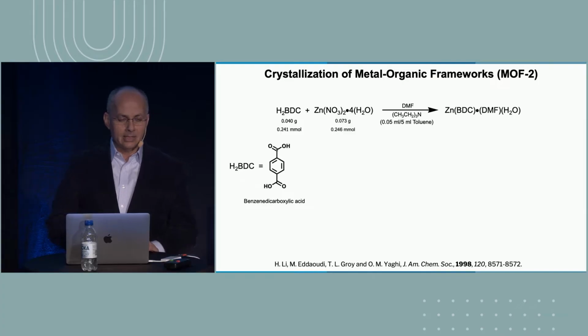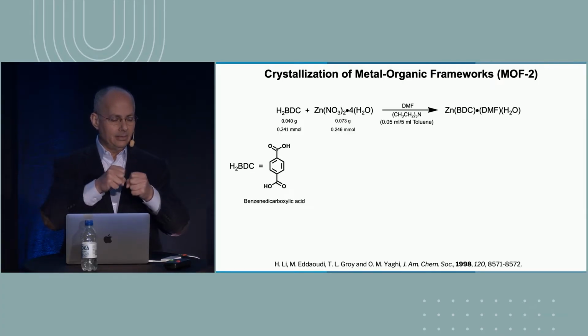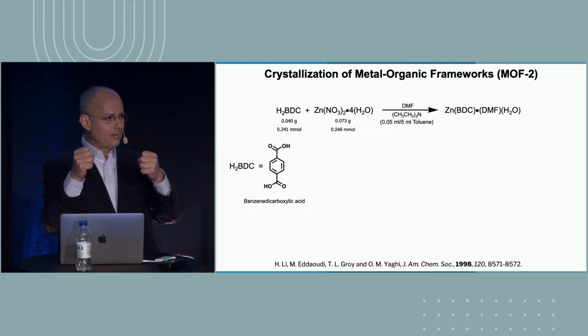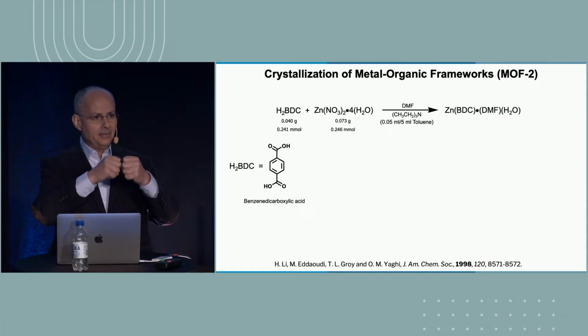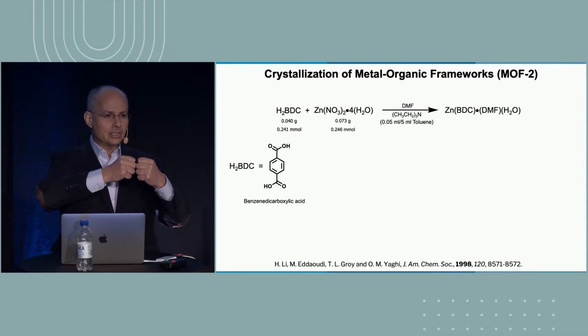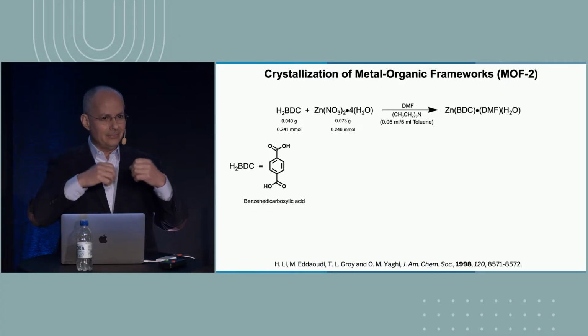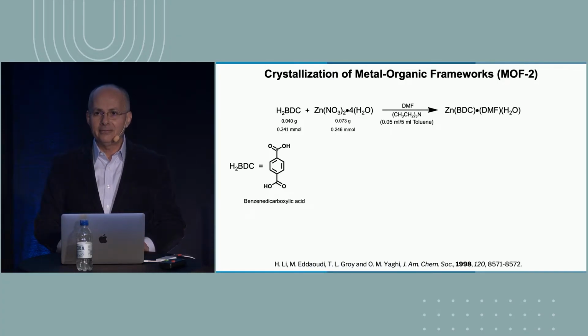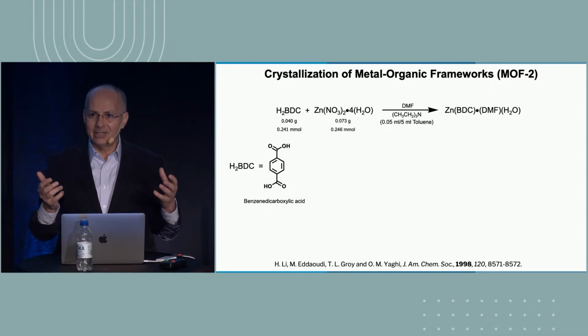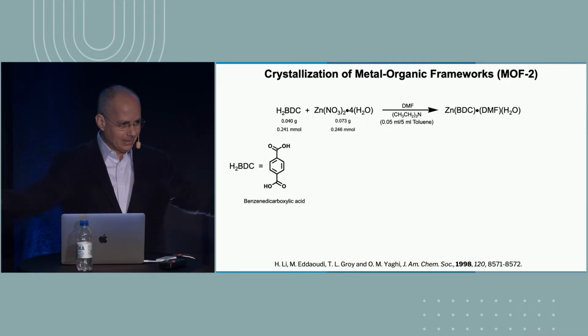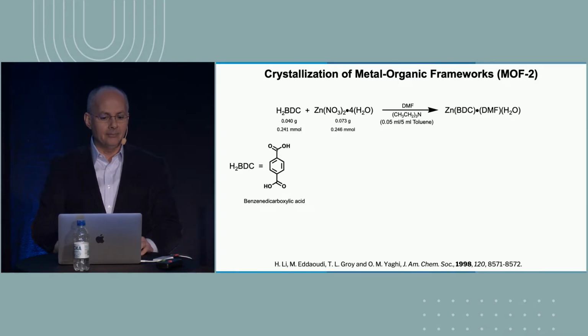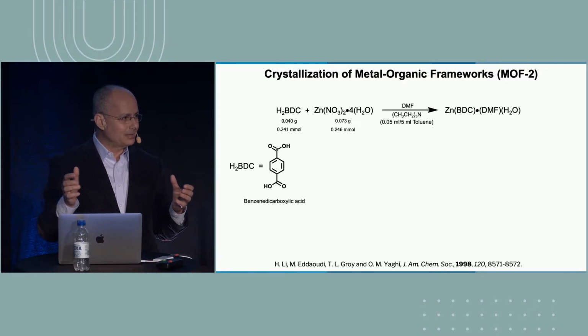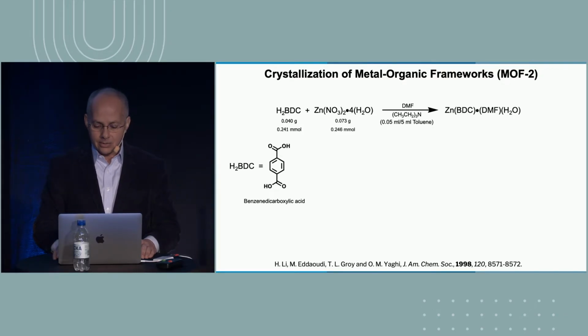Now, the key to crystallizing anything is to make sure that your building units can attach themselves and then break away while they're being crystallized, so that they can fix any mistakes. If they approach in the wrong geometry, they can detach and come back and fix. It's like asking you to go out in the field and make a big circle. That doesn't happen instantly. There's a lot of holding hands and correction to make that circle. It takes time. So you have to control the kinetics of your reaction. If the kinetics is too fast, then you make too many mistakes that there's no time to correct. If it's too slow, then you don't grow the material to the level that you want. And so these are the conditions.